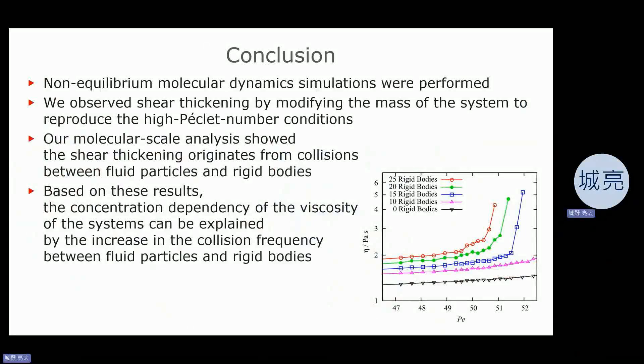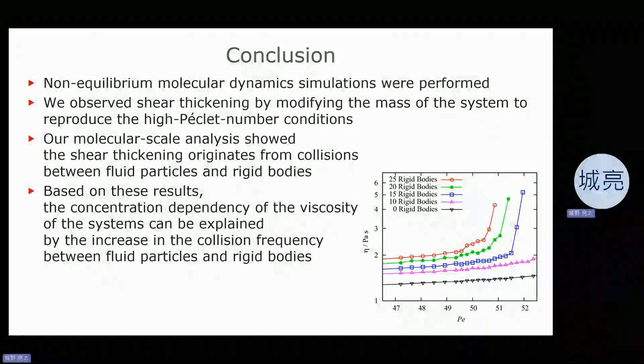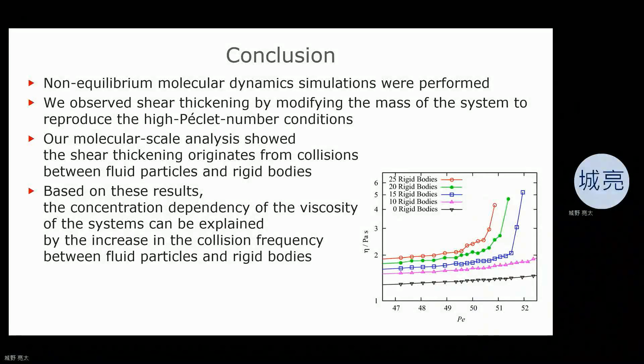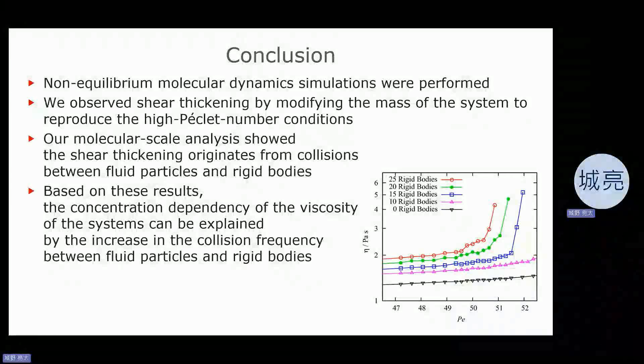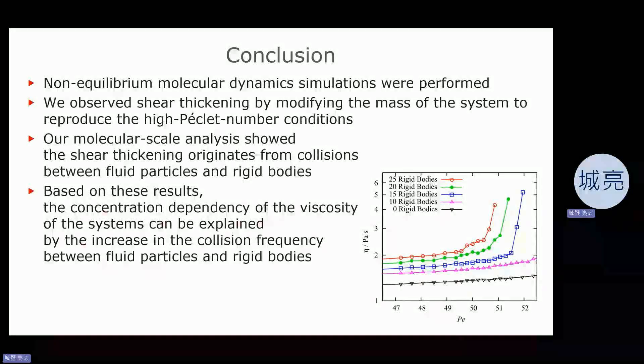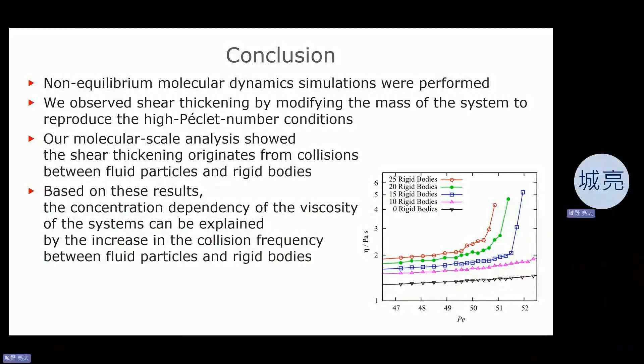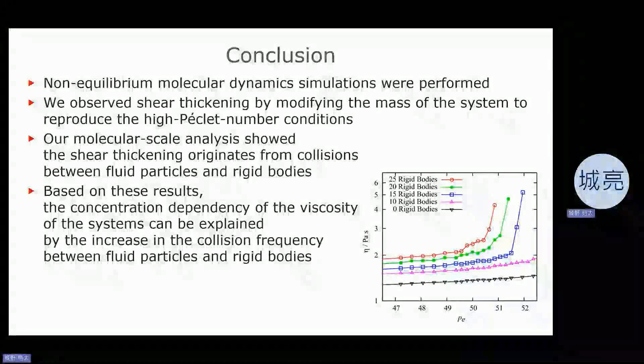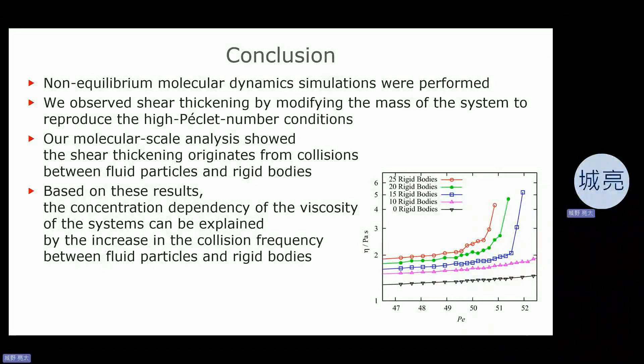This is the conclusion of my talk. Non-equilibrium molecular dynamic simulations were performed. We observed shear thickening by modifying the mass of the system to reproduce the Peclet number conditions. Our molecular scale analysis shows the shear thickening originates from collisions between fluid particles and rigid bodies. Based on these results, the concentration dependency of the viscosity of the system can be explained by the increase in the collision frequency between fluid particles and rigid bodies.